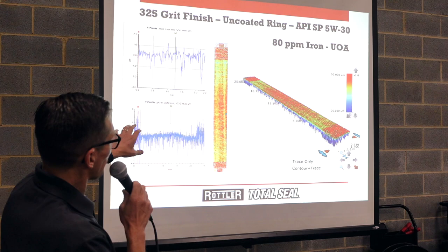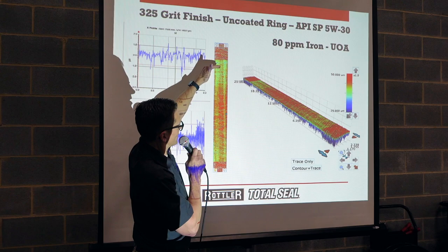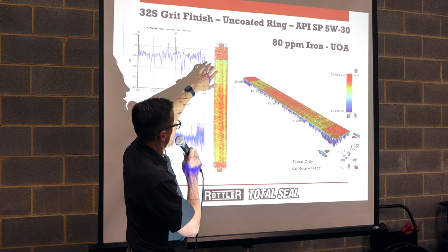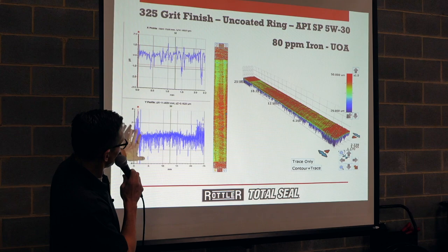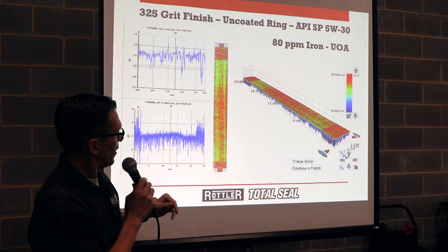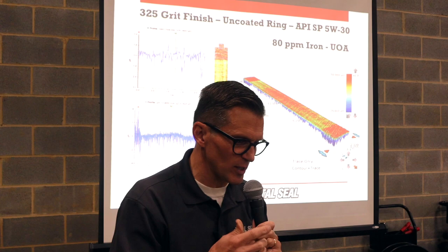And you can see the wear scar. This is the whole travel where the ring was going. This is top dead center, where there's going to be the highest amount of load. This is the bottom, where it's not going to be as much load. You can kind of see that. Unrun area, and on the seat, you can see the highest peaks on both of those. When you do the used oil analysis, because it runs in oil, we had 80 parts per million iron, which, of course, is an iron liner, so that's where it's going to come from.